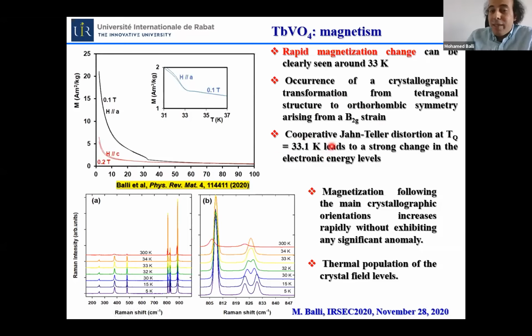And of course, this structural transformation associated with a cooperative Jahn-Teller distortion gives rise to, as can be seen here, a large magnetization along the A-axis and a strong magnetic anisotropy in these materials.